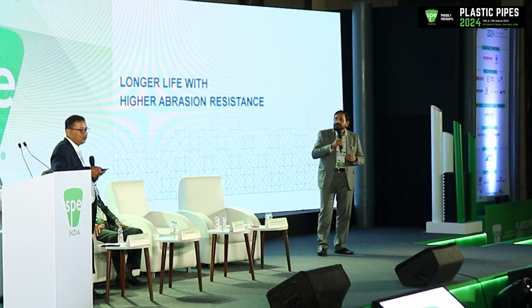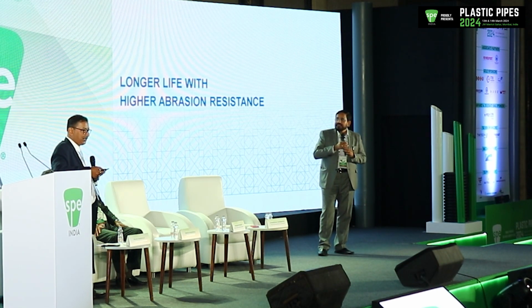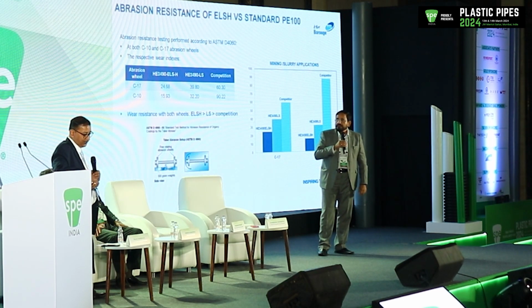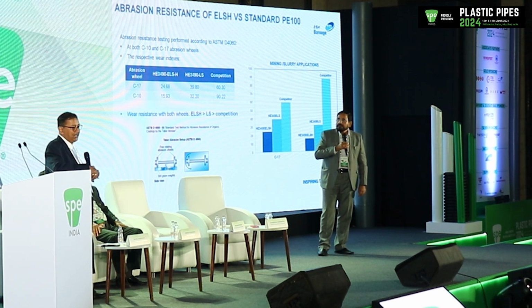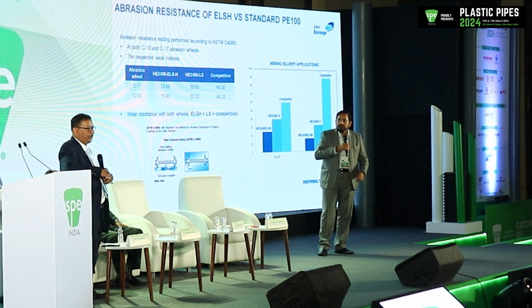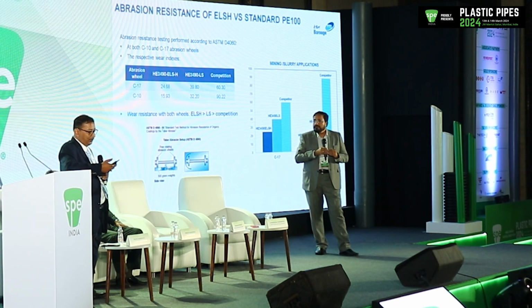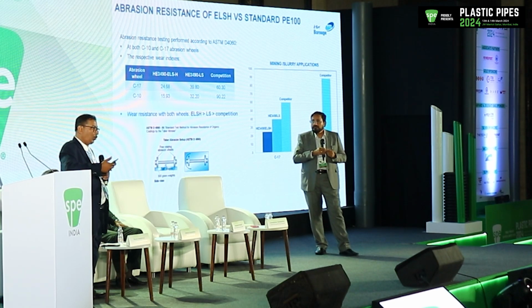So now we come to longer life with higher abrasion resistance and how that can give you cost saving and economic advantage. Now we have benchmarked these materials also for abrasion resistance because abrasion resistance increases with molecular weight. Higher molecular weight will have better abrasion resistance and also with longer side chain branches which will give more entanglement. So we have done abrasion resistance test as per ASTM D4060 using both C10 and C17 abrasion wheels.